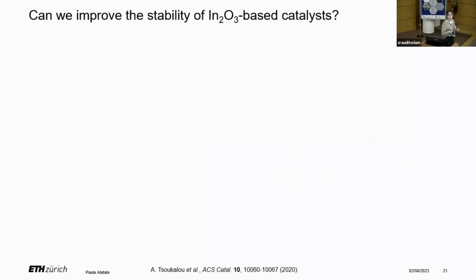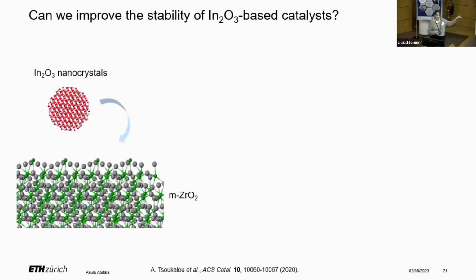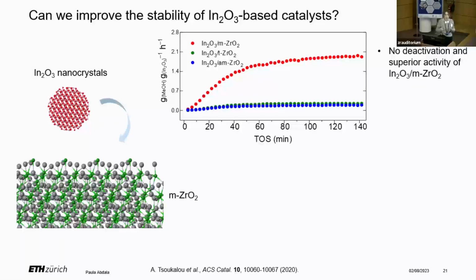So the question we ask ourselves is, can we stabilize the oxidation state of indium via catalyst design? We take a similar approach. We deposit the indium oxide nanocrystals, the same we have already studied, onto different metal oxides. And I'm going to focus on the most active one, which is when we deposit it onto monoclinic zirconia. And we see that indeed it stabilizes. And not only that, but it increases the methanol yield per indium content.